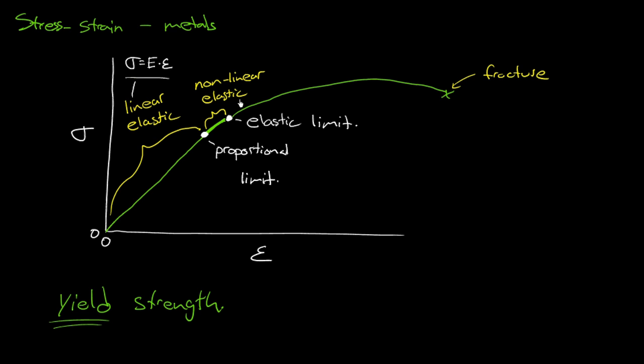And this elastic limit, although it's nice and clear to define because I've got this region of elasticity followed by, I'll label this as all plastic. That's clear to define because I've got this great big white dot there. But if this was a real curve, you wouldn't have a great big white dot there. In fact, it wouldn't even be obvious where the proportional limit is. So we need some standard to determine some of these features, particularly a property like this, like the yield strength. We need to define that.